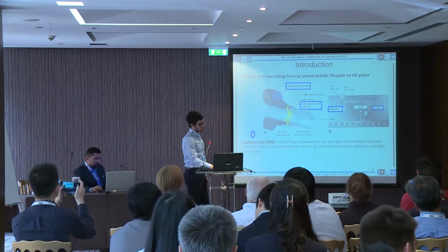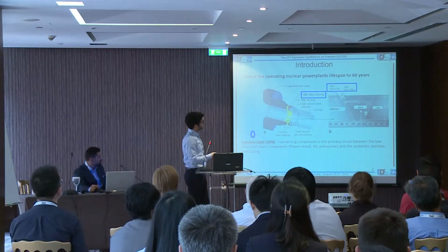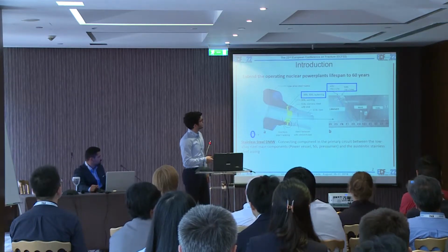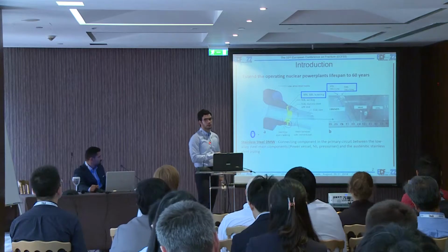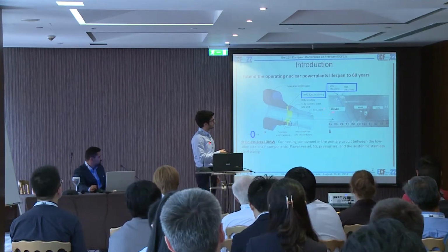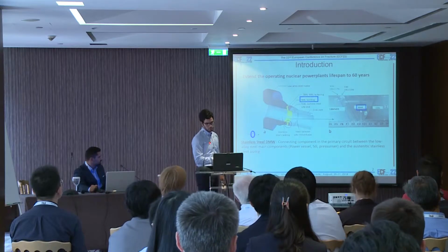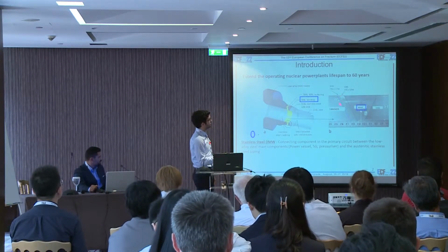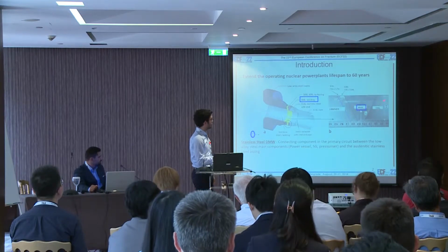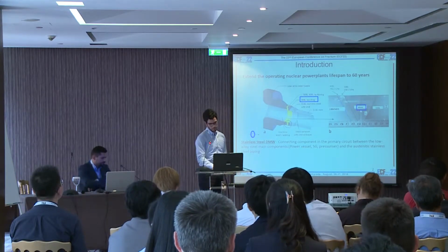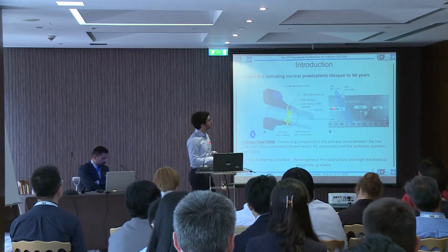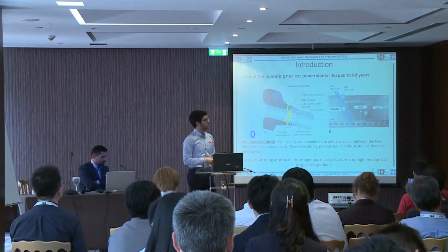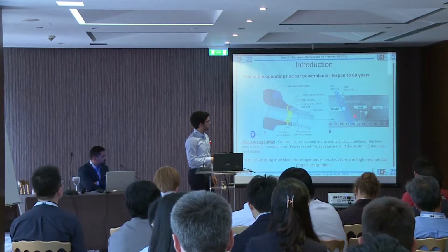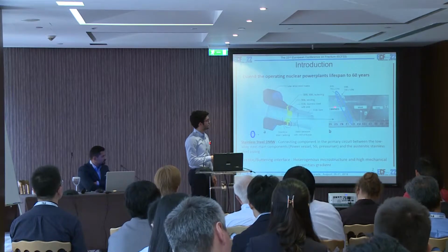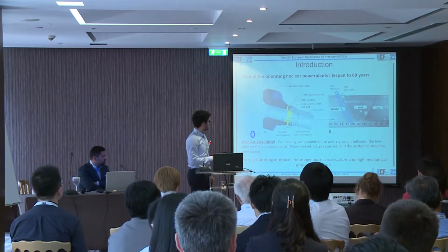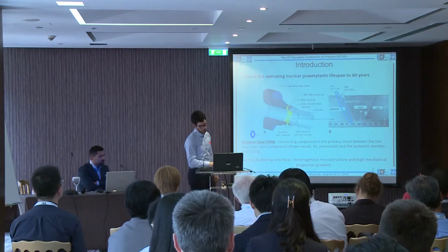As you can see in this photo, first of all, we perform what we call an austenitic buttering. It consists of several layers of austenitic steel deposited on the ferritic component, and then we perform the main TIG welding between the austenitic buttering and the austenitic stainless steel piping. As you can imagine, the biggest heterogeneities in microstructure and mechanical properties are concentrated in the interface between the ferritic component and the buttering. So in the rest of the study we will focus on this interface.